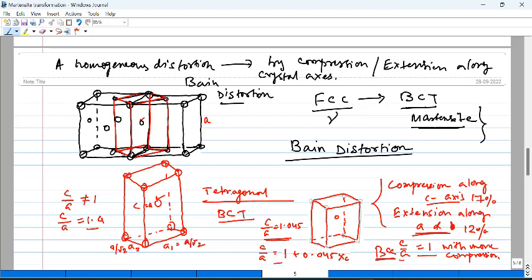And this is relevant to the Martensite transformation because you see this kind of change in the crystal structure without any change in the composition, right? By diffusionless, what you mean is that the composition of the austenite in terms of the carbon content is not changing. It is simply changing from one crystal structure, FCC, to another crystal structure, BCT.